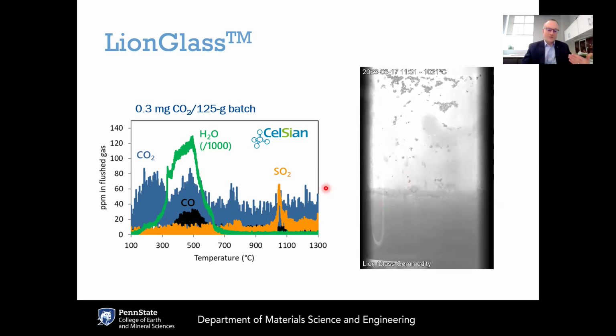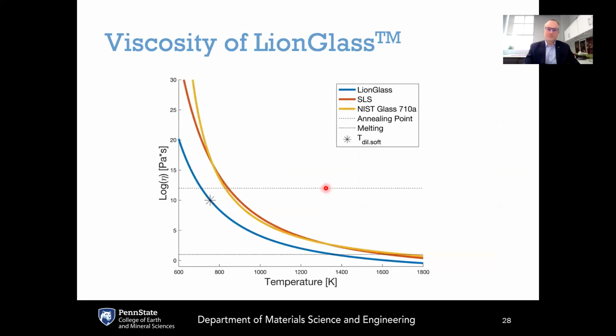So we are indeed able to eliminate CO2 from the batch to melt conversion process by eliminating carbonate batch materials and also lowering the melting temperature to reduce energy costs and the carbon footprint associated with energy. Of course, this is a result of the viscosity curve of LionGlass. These are MYEGA fits to the log viscosity versus temperature. You can see a couple of soda lime curves here in yellow and red, and then the LionGlass curve in blue, where the entire viscosity curve is shifted to lower temperatures.